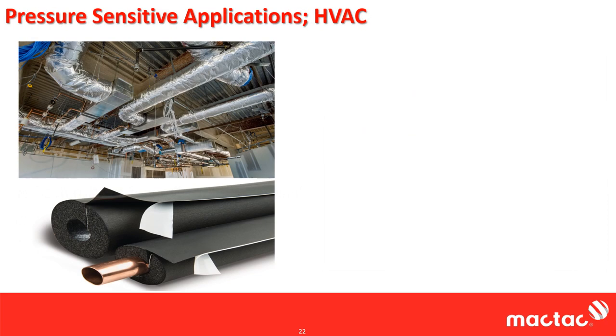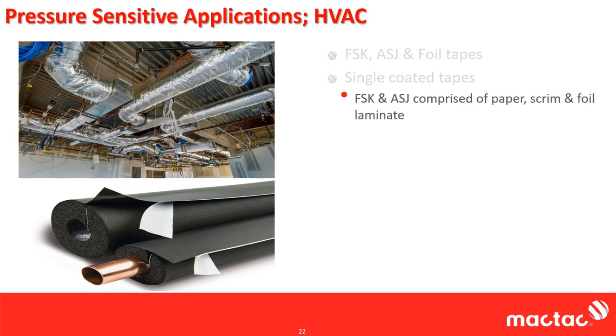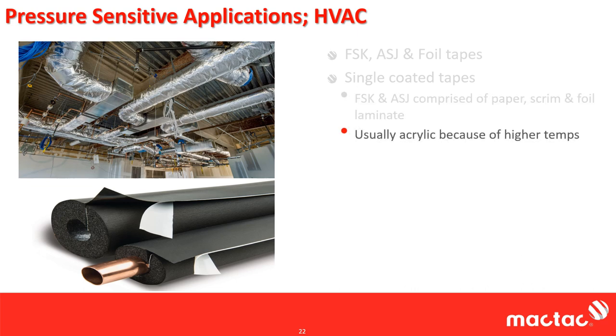One of the more well-known markets for pressure-sensitive adhesive tapes is the HVAC market. That's because this is a market where the applications just aren't practical for structural-based adhesives. FSK, ASJ, and foil tapes have been used in this market for decades. These are single-coated tapes. They are comprised of a paper, a scrim, and a foil laminated together and coated with an adhesive. Typically, these adhesives are acrylic because of the higher temperatures involved. Rubbers do not have good temperature resistance on the high end.